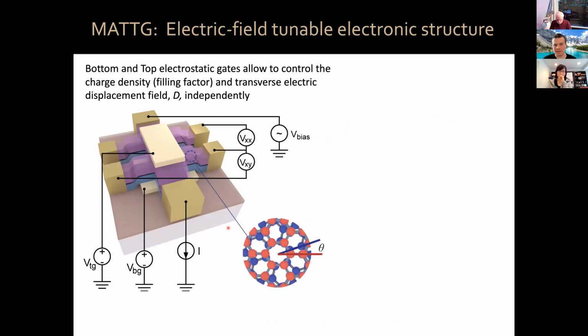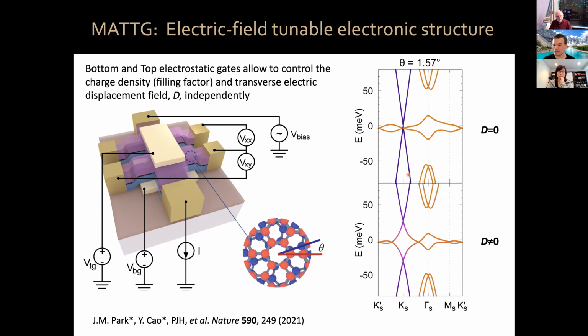Now, in our system, we have our magic angle twisted trilayer graphene, and we have top and bottom metallic electrodes. This allows us to independently vary the charge density in the twisted trilayer graphene, and also polarize the layers by applying a transverse displacement field by putting opposite voltages on the bottom and top electrodes. When you apply a transverse displacement field, then you break the mirror symmetry of the system. The top and the bottom layers are no longer symmetric, and as a result, your electronic structure now gets hybridized. Those two block diagonal terms now get hybridized, and your massless Dirac band and your magic angle bilayer graphene-like flat bands get hybridized, and this is tunable with displacement field. So the system is a lot more tunable.